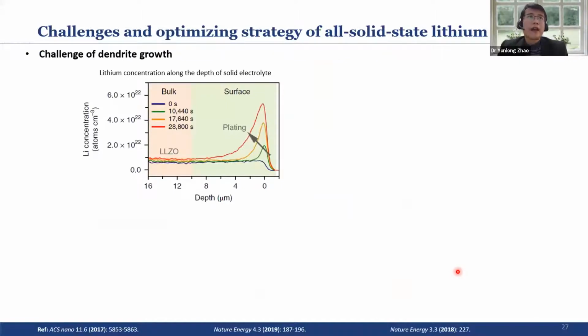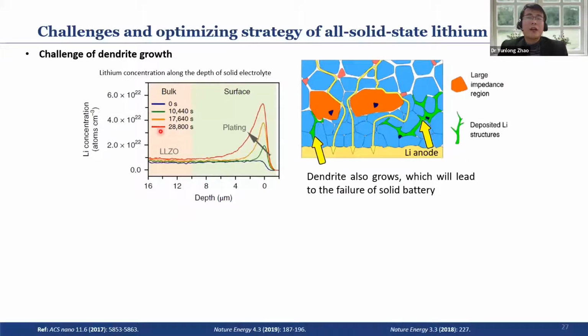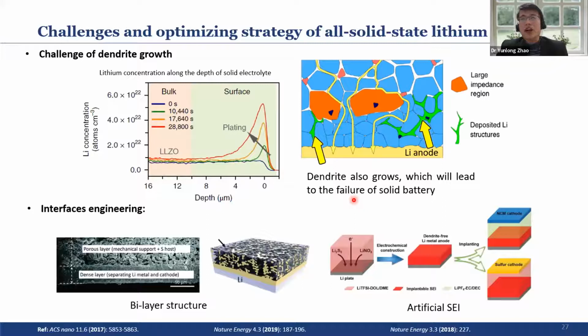Another challenge is dendrite growth. Recent research has found that ideally the solid electrolyte could allow the lithium to diffuse but stop the electrons. But some recent studies found that solid electrolytes still have very, very low, but still some electron conduction, which means lithium can create some dendrite growth. Those dendrites can even lead to failure of the solid batteries, especially if we use a large current. This kind of phenomenon is even more serious.